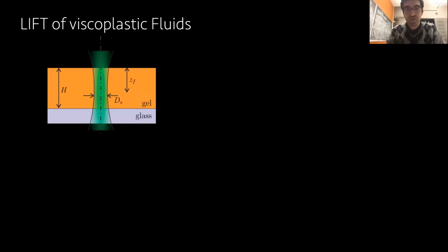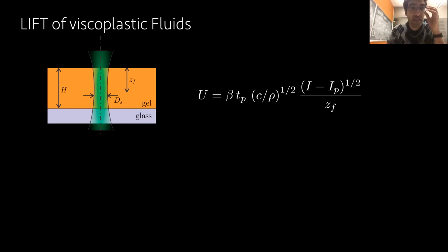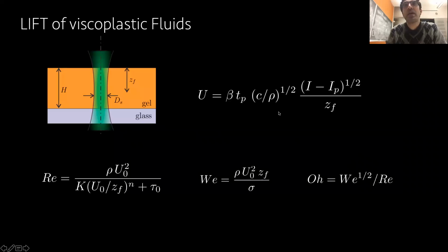Okay, we did a little bit of theory. I didn't go into the details, but we found a characteristic velocity of such a process by balancing the laser energy with other initial parameters in our problem. You get this characteristic velocity that has a lot of terms in it, but with that, you can now define your non-dimensional numbers that have yield stress and other rheological parameters too.